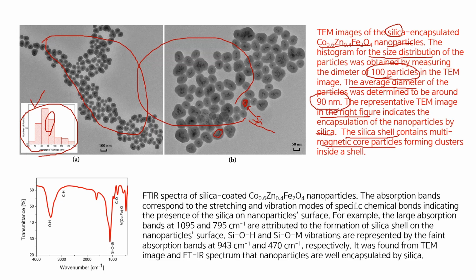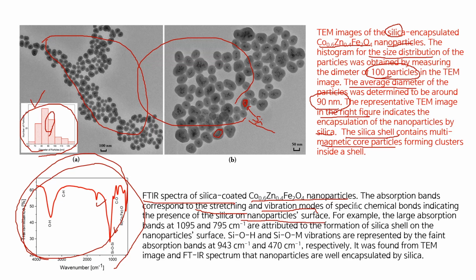Well, this FTIR spectra is the FTIR spectra of silica-coated cobalt zinc ferrite nanoparticles. The absorption bands, this one, correspond to the stretching and vibration modes of specific chemical bonds, indicating the presence of silica on the nanoparticle surface. So, using this FTIR spectra, we can confirm that silica is well coated on the surface of magnetic nanoparticles.